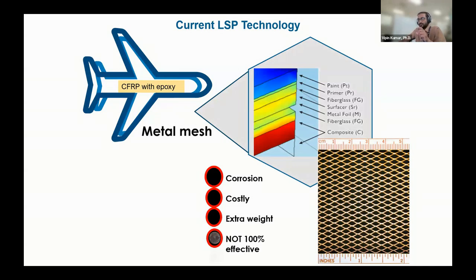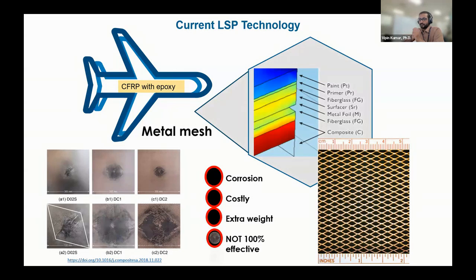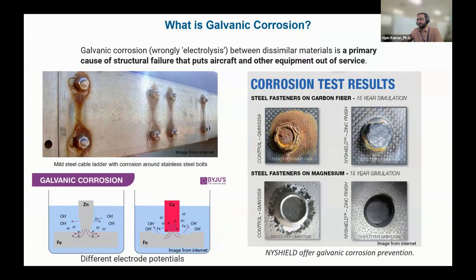And although you want to put this metal mesh, it's not just a metal mesh that you stick to the composite. It takes a little bit more than that. It comes with multiple layers, and you have to create a barrier between the metal and the carbon. The reason is you can get galvanic corrosion. Even on top of that, the metal mesh is usually not 100% effective. It does reduce the lightning damage significantly, but it still creates some kind of scarf damage, and then you have to repair it. And as I mentioned, metals and carbon together don't like each other. So either you need to create an insulation layer between them, or you have to reduce their electrical potential to reduce the galvanic corrosion between metal and carbon.